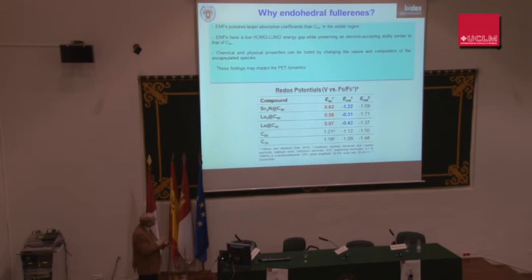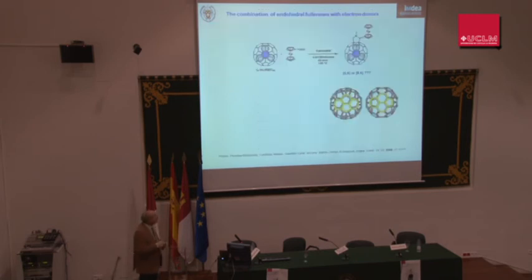Now here you can see some examples. What I'm showing you here is for C60 and C70 the oxidation potential and the reduction potential, which are quite similar. So when you change C60 to C70, you are slightly modifying the electronic properties. But look at this, just by using endohedral fullerenes, you are dramatically modifying the electronic properties. Actually, look at this, it's a very, very powerful electron donor species. This is a very, very powerful electron acceptor species. So you are controlling and modifying at will the energy gap. And this is an important matter. Actually, we reported the first example a few years ago, in a joint project in collaboration with Tomás Torres, Luis Echegoyen, and Dirk Guldi, who carried out the photophysical experiments. But we carried out the covalent connectivity of an electron donor molecule like ferrocene to the scandium nitride endohedral fullerene.